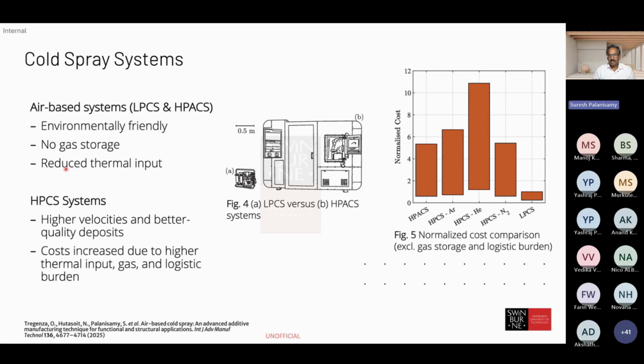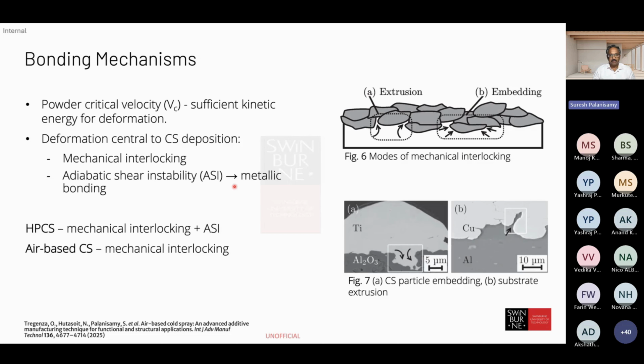And also the low pressure system is comparatively much cheaper because of the application areas where it is used, and also there is less need of high temperature or highly compressed air. So that's what you can see in the size or the dimension of the equipment. The low pressure system can be very small, half a meter to a meter, and in some cases it's a portable system. Obviously with a high pressure system, you need a large enclosed section to avoid any damage to the external environment. So that's why the cost also varies compared with the low pressure system, which can be mobile and taken on site for repair and different coating applications.